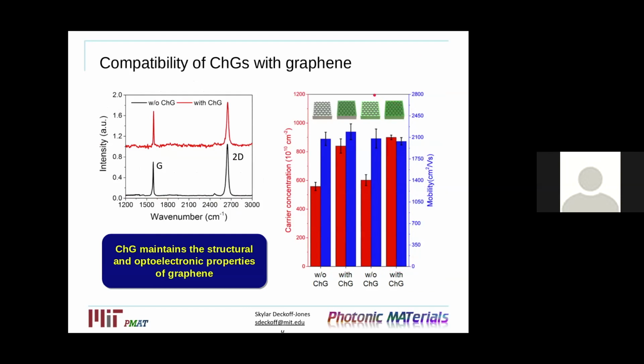And additionally, further, we look at the mobility and carrier concentration of graphene with 4 different samples. So one just on silicon dioxide, one with the chalcogenide glass just on top, one with the chalcogenide glass just on bottom, and then one that's sandwiched in the chalcogenide glass. And impressively, across all the samples, although we do see a change in the carrier concentration, we don't see a change in the mobility, which is very common, for example, when you deposit other dielectrics, that you get a degradation in the mobility of graphene. So this is an achievement which can be attributed to likely the low thermal budget and low deposition temperatures of the chalcogenide glasses.